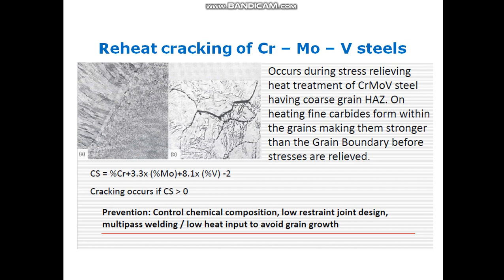Well, reheat cracking of chrome moly vanadium steel is also a phenomenon that happens during the stress relieving heat treatment, particularly in chrome moly vanadium steel. If the chrome moly vanadium steels have a coarse grain heat affected zone, upon heating, fine carbides form within the grains, so they make the grain stronger than the grain boundary. Under the stress relaxation process, the weaker grain boundary cannot withstand the stresses, and the grains are separated from each other. This is known as reheat cracking, or sometimes known as post-weld heat treatment cracking.